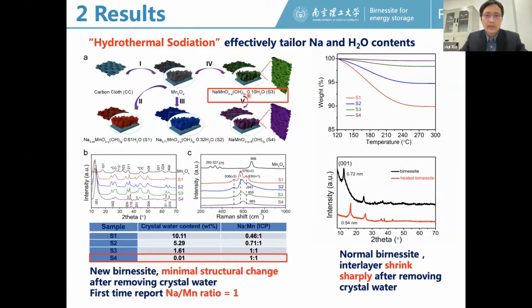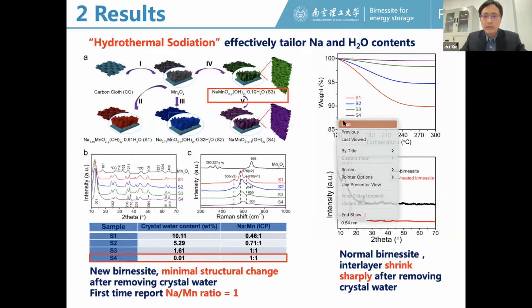And for this high sodium content sample, S3, we further anneal it in the argon atmosphere to remove all the crystal water. So from this TGA result, we can see that for the S4 sample, there is no crystal water at the interlayer. Then we find an interesting phenomenon.